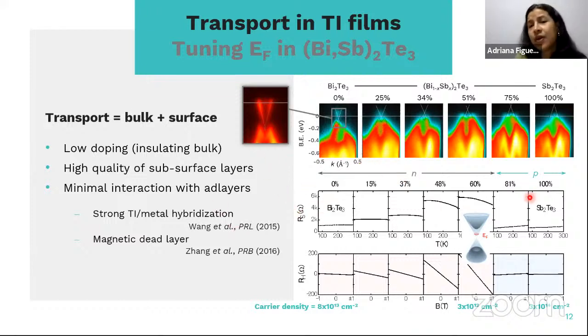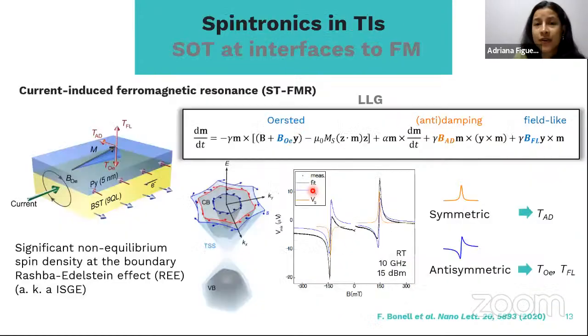And then once we've established the optimal conditions for this BST material to use in transport measurements, we can now incorporate it into heterostructures with magnetic materials, because we are interested, as I said, in exploring the spintronic properties. So the first study that I'm going to show you today is about spintronics in TIs, in particular about spin orbit torque at interfaces of the TIs with ferromagnetic materials. In this case, the ferromagnetic material that we used was permalloy, which is an alloy of iron and nickel.